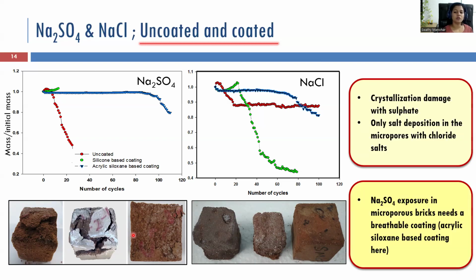Coming to the coating, sodium sulfate exposure in microporous bricks, which are more damaging, needs a breathable coating. It should be a breathable coating compatible to the matrix, which is found as acrylic siloxane based coating here.